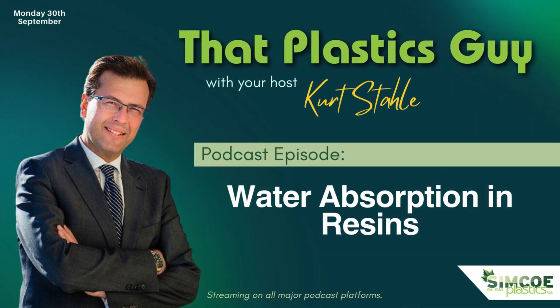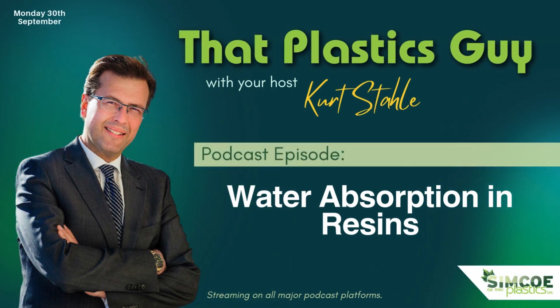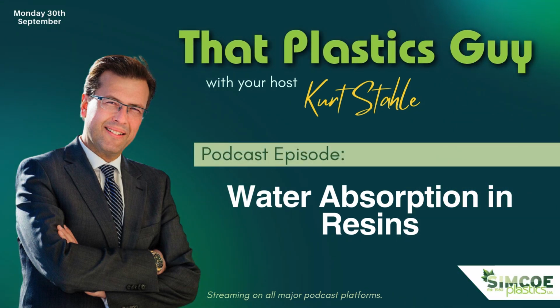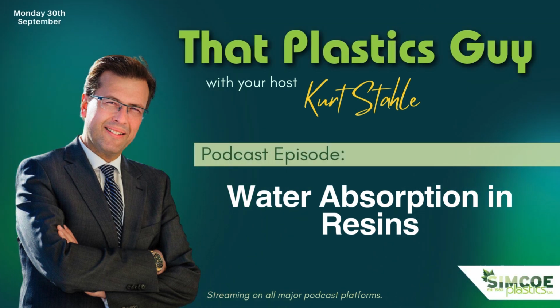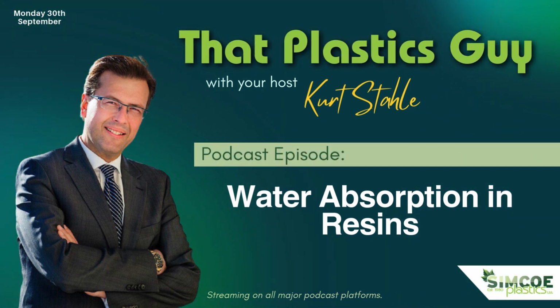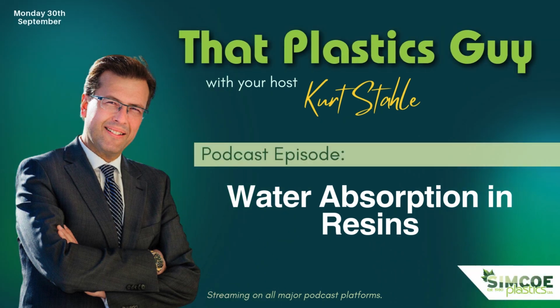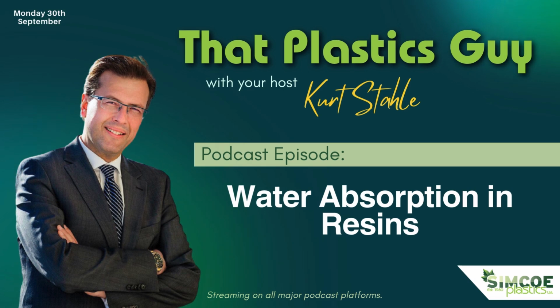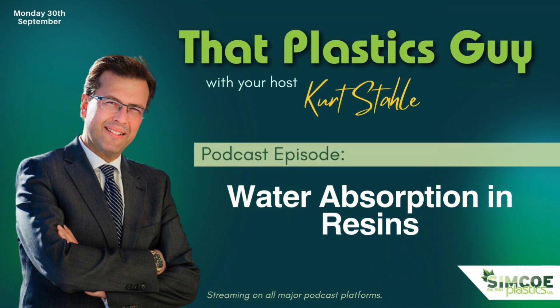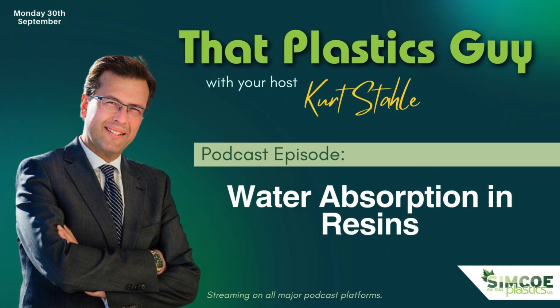Polyolefins, polypropylene, polyethylene, contain no chemical bonds that are easily influenced by water or hydrolyzable. There you go. There's the word of the day, hydrolyzable. Hence, they absorb little water and essentially are unaffected by aging in water. And of course, that's why we see polyethylene specifically in blow molding applications used for transporting household cleaning products, motor oil, basically everything that you see at a typical department store, polyethylene blow molded, and it just doesn't seem to be affected at all by any contact with liquid. In fact, it's got excellent chemical resistance.